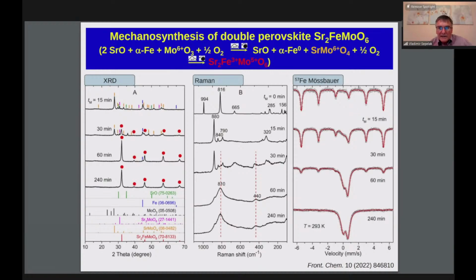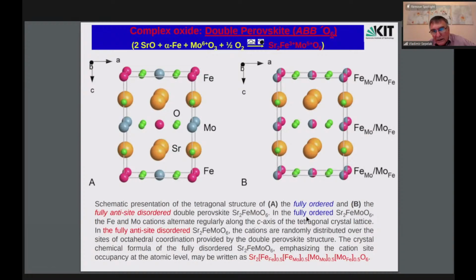Yeah, you are right that in many cases we produce not only defects on the level of cations, like in the case of perovskites, anti-site disorder, but we also produce defects on the level of the anionic sublattice, oxygen vacancies. I cannot give you the exact value of delta, but I suppose that there is some concentration of vacancies on the oxygen sublattice. If we measure X-ray diffraction or other methods, it is always perovskite. It is a rather stable structure. We do not know the exact number of vacancies on the oxygen sublattice.